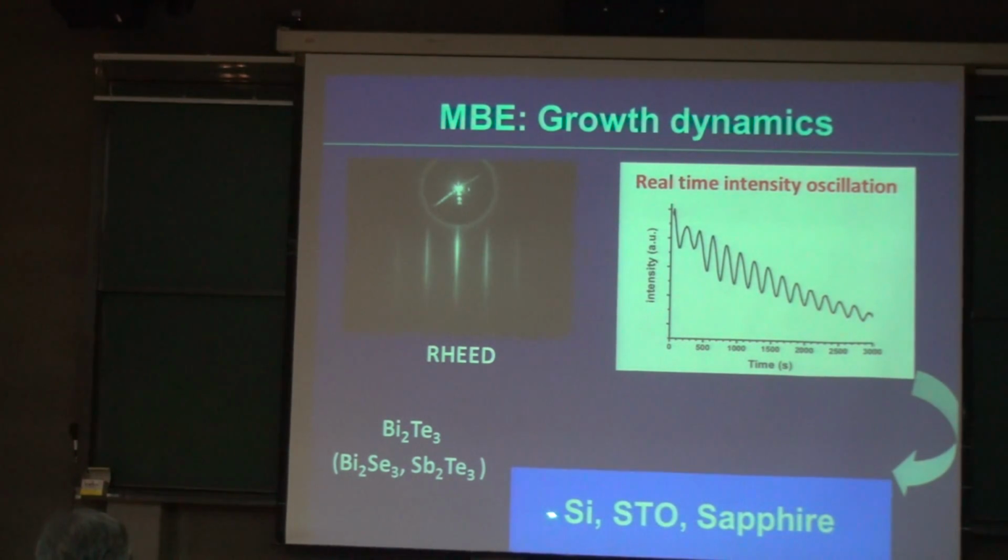So this is the reflection high energy electron diffraction pattern during growth of the bismuth selenide. You can see this is the 0,0 diffraction, 0,1, this is 0,-1. Along all these diffractions you have this very long bright line. If you know the principle of this diffraction, the very long straight line indicates the morphology of the film is very flat.